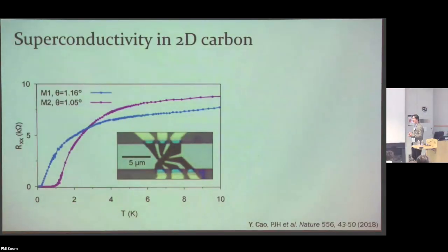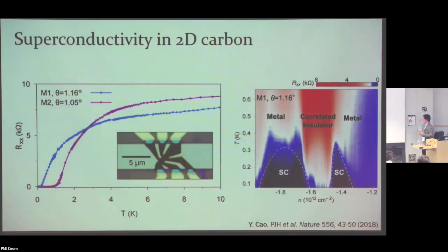So this is actually also what happens in this twisted bilayer graphene system as well. And very surprisingly, what we found is that when you slightly dope away from this correlated insulator state, you also get a superconducting state with TC up to about 2 Kelvin or so. There's a lot of following study on this about the strength of the superconductivity, the pairing symmetry, also about whether there are nodes in the superconducting state, which I won't go into in detail.